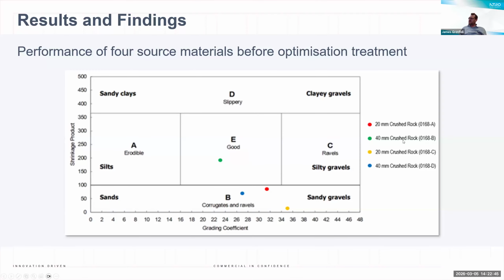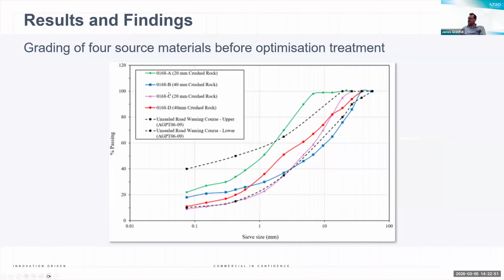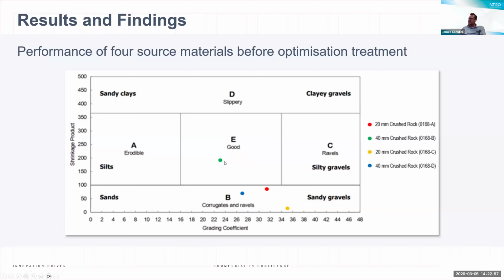So actually, this green one we'd expect to perform well. Actually, looking at whether those lines are slightly different colors, aren't they? So the B material is actually the one that performs the best, sits within the good area. And then the other 3 are all potentially at risk of corrugating or raveling when used in the field. So straight away, that leads us to understand, okay, so of their 4 available materials, one of them is likely to perform well. The other 3 potentially are going to be at risk of corrugations and raveling and potentially aren't going to perform very well at all.